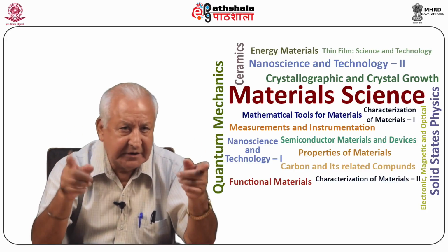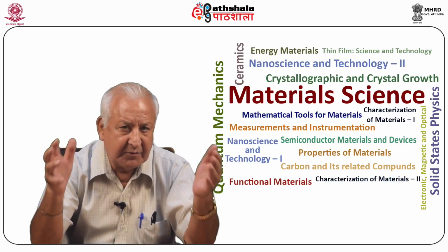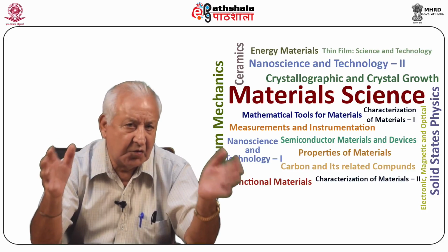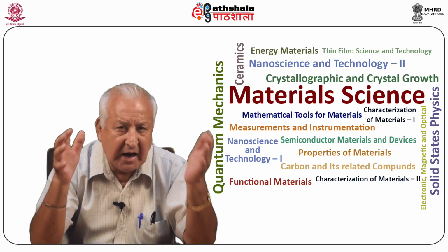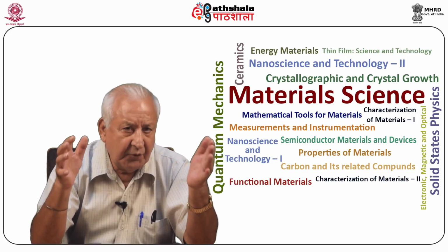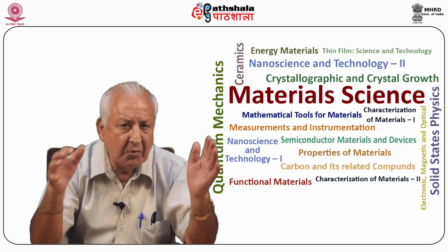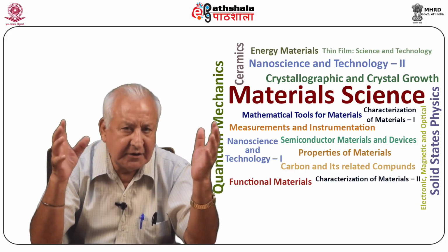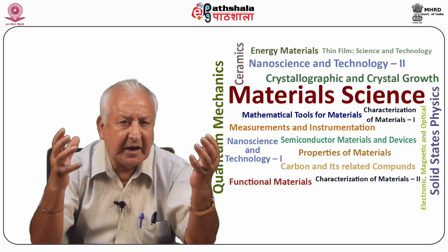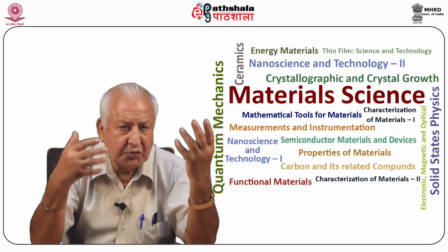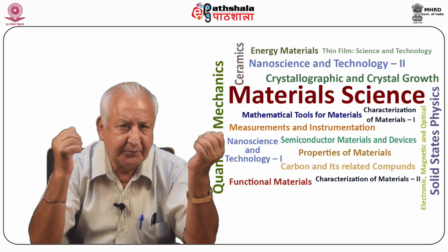In the case of materials having higher melting points, the nutrient zone is maintained at about a temperature which is 50 to 150 degrees centigrade more than the temperature at the growth zone, which may be around 800 to 1200 degrees centigrade.